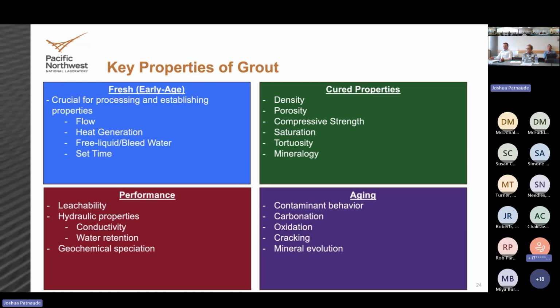The more practical and representative tests are the semi-dynamic leach tests, where we take a sample that's now not crushed, monolithic, put it into a solution of water, let it sit for a period of days, and measure how much stuff is coming out. Being immersed in a large bath is still a very conservative scenario for a grout waste form, but it gives us very valuable information to compare rates of release of different contaminants and see if the mechanisms that we've entered into it last for several days, several weeks, several months, several years. It gives us data that we can model against. And we can do those exposures in different pHs or different groundwater environments to see how things change.